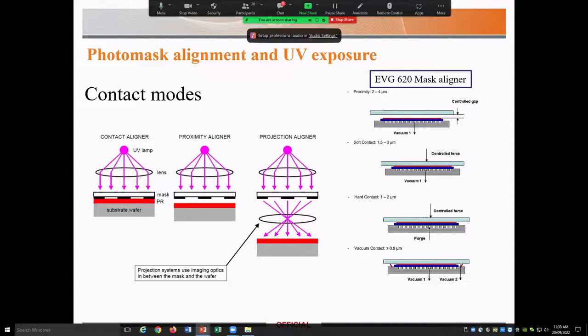There are three primary exposure modes in a mask aligner. In contact mode, the wafer is brought into physical contact with the photomask. So it gives us very good resolution, but fragments can be trapped between the photomask and wafer, and we may have potential damage to the pattern on the photomask, which can give us defects on the photoresist pattern.